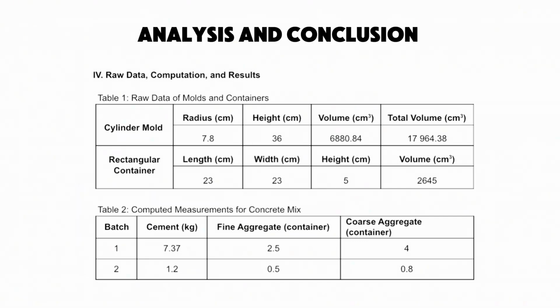The computed material requirements for batch 1 included 5.71 kilograms of cement, 2 containers of fine aggregate, 3 containers of coarse aggregate, and 3.3 liters of water. While batch 2 required 1.2 kilograms of cement, 0.5 containers of fine aggregate, 0.8 containers of coarse aggregate, and 0.7 liters of water. The water content adhered to the 0.58 water-cement ratio from DPWH Blue Book, ensuring compliance with construction